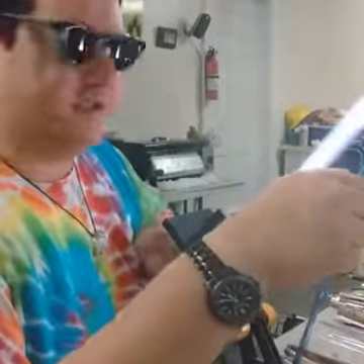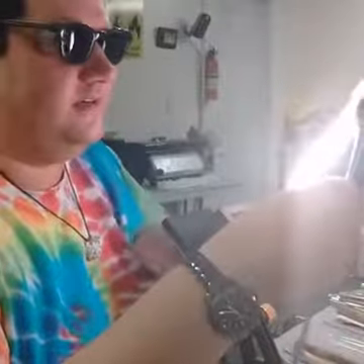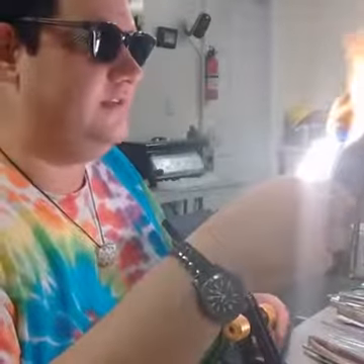So I'm going to go ahead and just preheat this tube. This tube is as cold as it is in the shop, and so I'm just using kind of an annealing flame here, which is just a high propane flame, a relatively cool flame, and that'll allow the glass's temperature to kind of normalize and equalize and get it closer to a working temperature. So there again, it doesn't blow up in our faces.